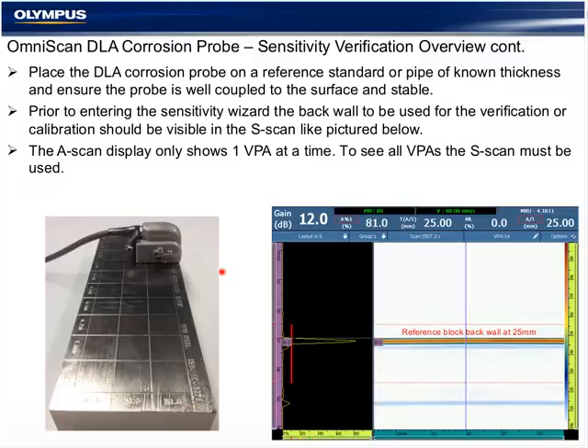The sensitivity calibration ensures that the A-scan amplitude across the first A-scan on this side of the probe here and the last A-scan on the far side of the probe here are equal or very close in sensitivity.